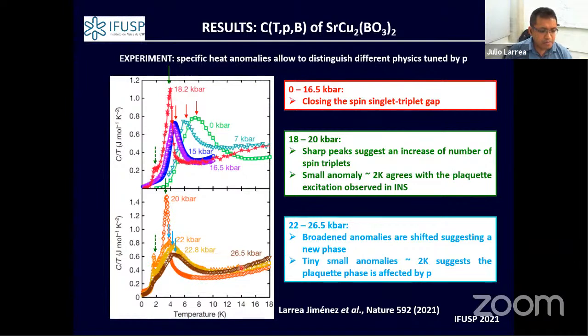This continues up to 26.5 kilobar, the limit of pressure in this experiment. After that, the small peak starts to decrease but stays at almost the same temperature.